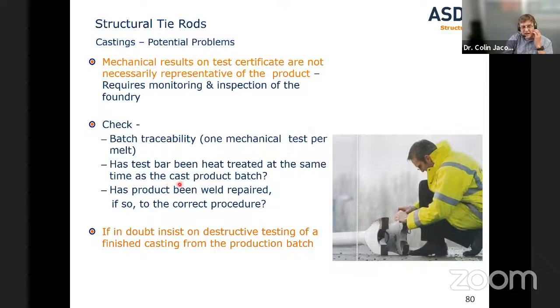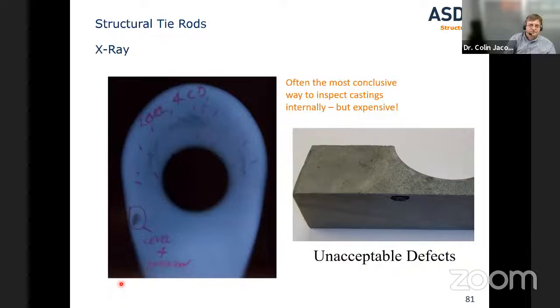Check that the test bar has been heat treated at the same time. Has the product been weld repaired? On some structures, you would need to know that and make sure it's the correct procedure. If you're ever in doubt on a project, just order a destructive test on an actual casting from the production batch. This will tell you whether you've met the requirements.